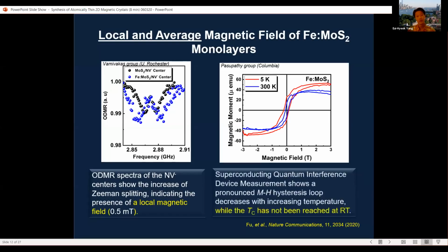For the average magnetic field, we use a superconducting quantum interference device measurement, and that shows a pronounced magnetic hysteresis loop, which of course decreases with increasing temperature, while the Curie temperature has not been reached at room temperature. So we have confirmed that the material is magnetized all the way up to room temperature.